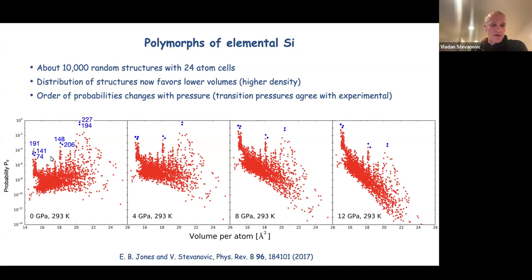Then what you can see here is that there are three peaks in this distribution. At the top of the rightmost peak is the diamond and the hexagonal diamond, which is also an experimentally realized structure in elemental silicon. The structures at the top of the other peaks are known high-pressure phases. And if in the Boltzmann factor you put the enthalpy and then start increasing the pressure to, let's say, 4 gigapascals, then you see that the probability distribution will start favoring denser structures. They will grow in probability, so that at about 10 gigapascals, the leftmost peak will become dominant in terms of probability. And this corresponds fairly well with the transition pressures for these structures that are observed experimentally.